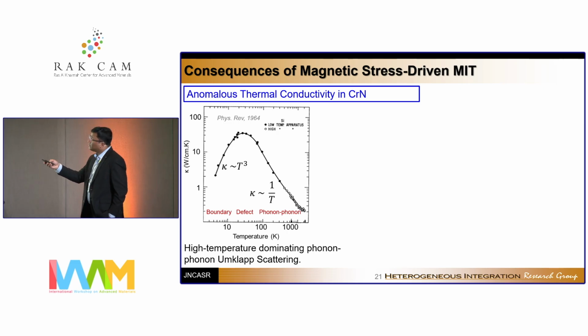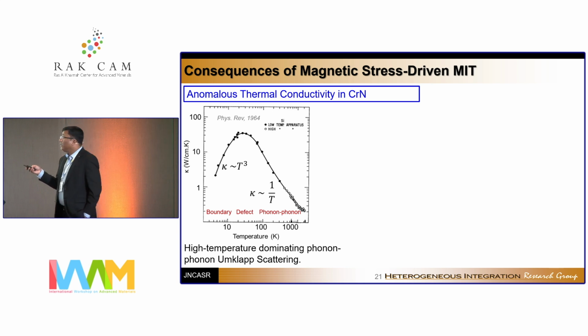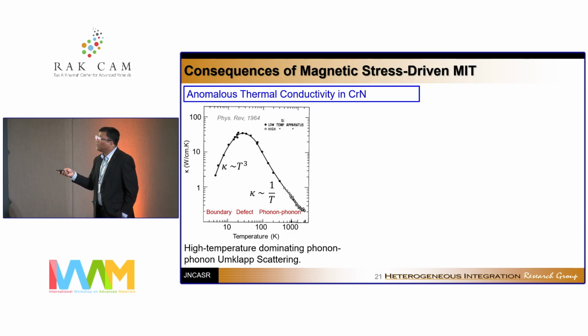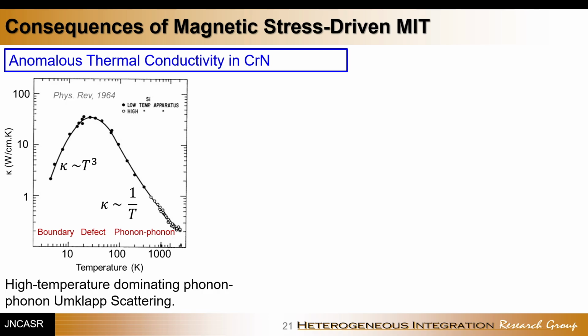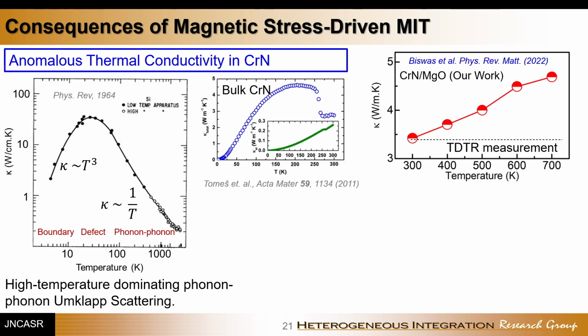The second thing we looked at is, as a consequence of the metal insulator transition, what we found is that generally in most materials, if you measure thermal conductivity as a function of temperature, thermal conductivity actually goes down with increasing temperature. And that's because of Umklapp scattering, or phonon-phonon scattering. But in bulk chromium nitride, as well as in chromium nitride thin film, the phonon thermal conductivity actually goes up. And that is quite anomalous because you can't use the normal phonon-phonon picture to explain this behavior.